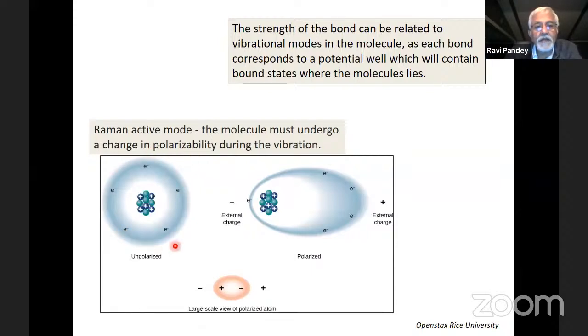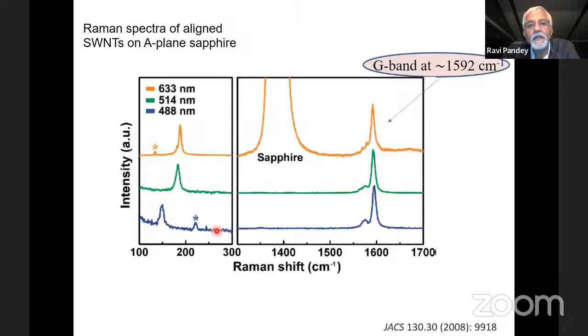So if we have an unpolarized electronic cloud, and it becomes polarized in an external field, then this transition provides the so-called Raman active mode for a given system. For carbon nanotubes, we call it the G band, which is about 1592 centimeter inverse. Both the location and the height of this band tell you how good the carbon nanotubes you have grown in the system are. So that's a quality check for the given sample.